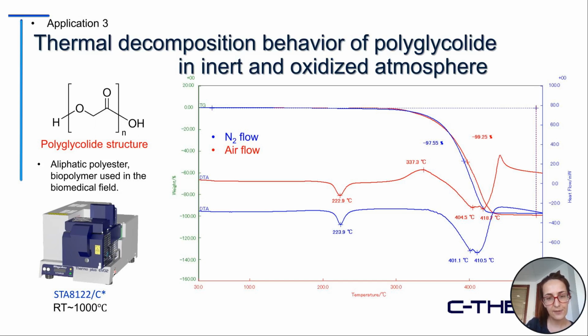However, in the DTA curve, we can see an endothermic peak at around 222, followed by an exothermic peak and two endothermic peaks, which is related to the melting of the polyglycolide in the airflow. However, in the nitrogen atmosphere, we couldn't see the exothermic peak around 337.3 centigrade, which is related to the oxidation of these samples in the airflow.